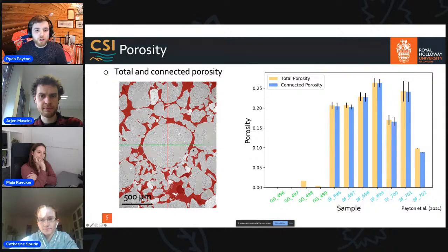We can also then run, through the full 3D image stack, an algorithm which will determine how much connected pore space there is. And we can see that the connected pore space here in blue is very similar to the total porosity in the case of the Sellafield samples. And this is really interesting, and I'll show you why in the coming slides. However, because there was no connected porosity at all in the Glasgow samples, we can determine straight away that this isn't really a suitable site for looking at carbon storage as a type of low carbon technology for this particular observatory.